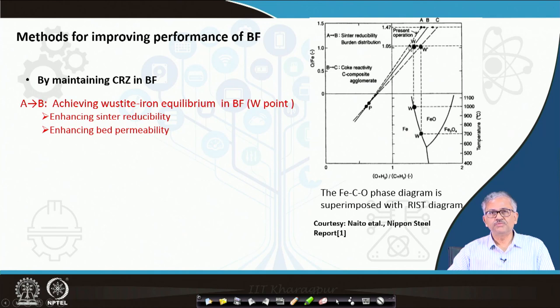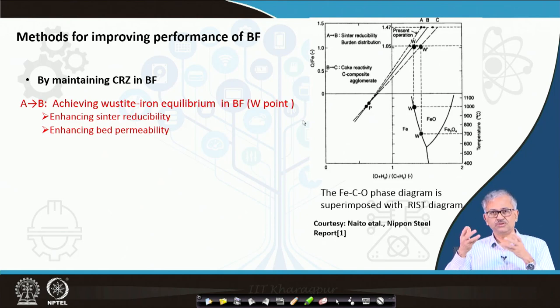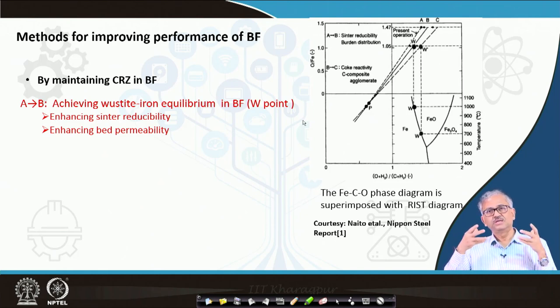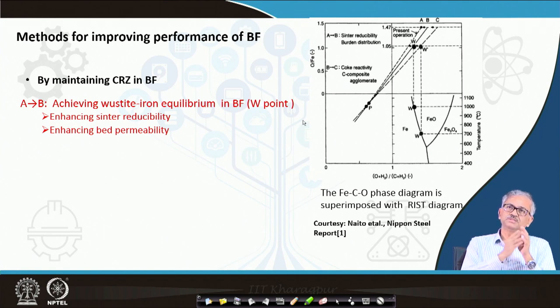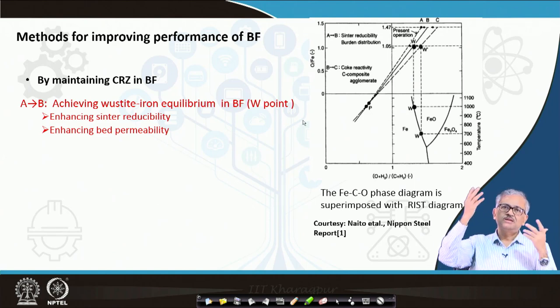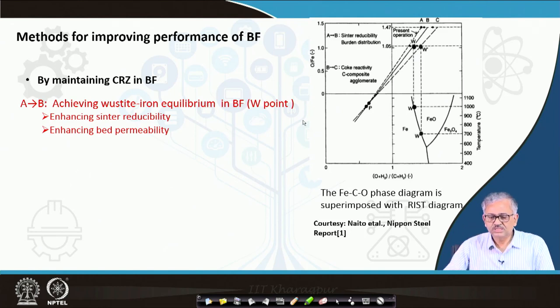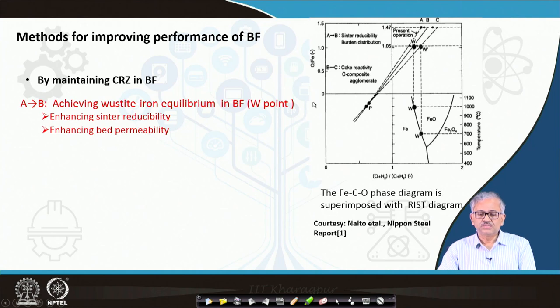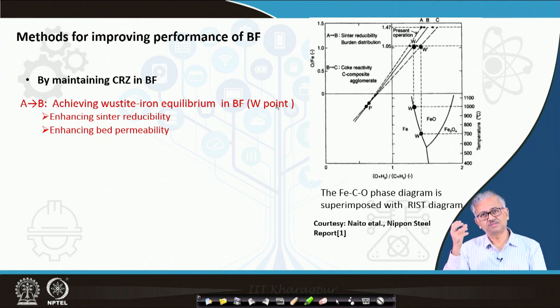We can move from A to B by increasing the reactivity of the iron ore — the sinter. If you have a more reactive sinter, you can ensure the chemical reserve zone will exist, because iron has to react fast within the residence time. The blast furnace is a plug flow reactor, and the residence time in the isothermal zone is not very high, so you may not attain the equilibrium unless you have very high ore reactivity.